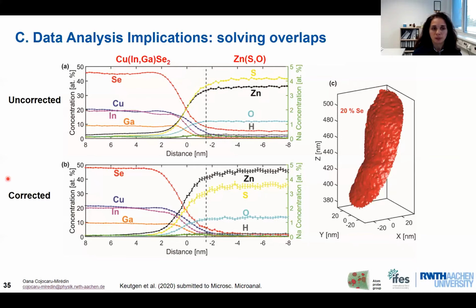By correcting the proxygram, we see clearly that we have zinc content which approaches 50%, and then we have almost no selenium inside the zinc sulfur oxygen buffer layer. So right now we are confident with these results. They also fit very nicely with what has been observed by other characterization techniques. And we know that this method is pretty reliable to resolve peak overlaps on the mass spectra on very defined volumes.